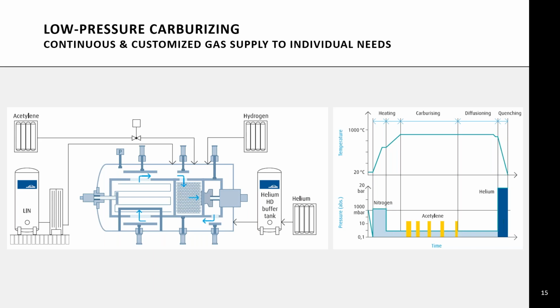The use of acetylene as a carburizing medium has specific advantages as well. With acetylene, the density of the loads is increased, as well as the length to diameter ratio of blind holes. So you can actually get carburizing a little bit further up into blind holes, such as ring gears and things of that nature for their mounting hardware. It also ensures the right flow conditions and supports intermittent flows, both low and high pressure, which is especially critical when several treatment chambers are present, kind of similar to the image here.